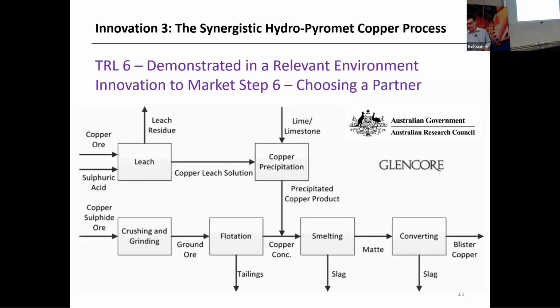The third one is the synergistic hydropyromet copper process. Here we were collaborating with the pyrometallurgy research group, understanding some of the challenges with smelting around lots of pyrite in there. There's overheating, the refractory bricks wearing out faster than you want. So the question was how do you cool down the smelter without putting in lots of slag recycling and dead volume? So we came up with the concept of leaching copper.